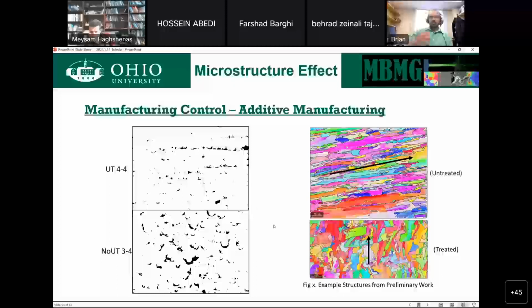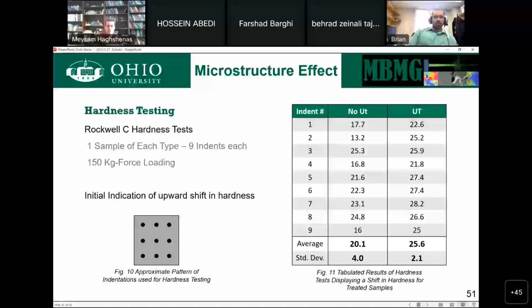Now, what we also discovered by accident when we set up one of our experiments is if you're not sending a high enough intensity, you will not see this grain refinement effect. But you will still see an increase in your material properties because you're affecting the sub-grain structure as you do so. So there's actually two effects that are going on here. And there is a publication in the works addressing that, which should be coming out in the next month or two.